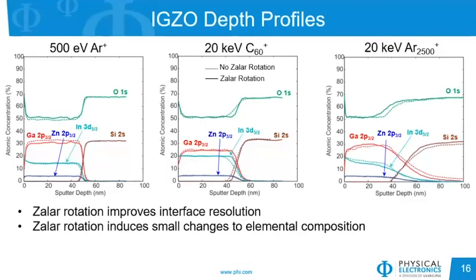We can also take into consideration things like the effect of Zalar rotation by rotating our sample and how that can improve our interface quality for these types of profiles. You'll notice that for the Zalar rotation, which is the bold line, compared to the non-Zalar rotated, which is the dashed line, with Zalar rotation on this system, we do see sharper interfaces as shown in the monoatomic argon and the C60 profiles, and also with the GCIB.